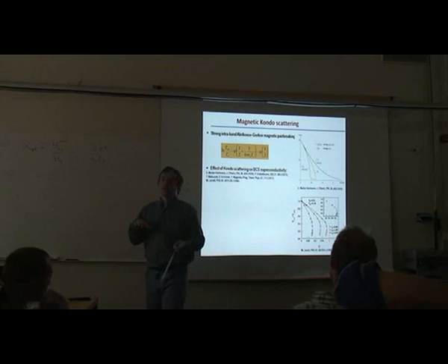And that is based on old theory of Kondo effects in a single band superconductor. In a single band superconductor, the theory of the Kondo effect has been developed in the 70s. And the answer depends on the ratio, basically, the Kondo temperature divided by Tc. If the Kondo temperature is much larger than Tc, then the Kondo interaction screens this scattering, reducing the pair breaking effect. So then, if the Born approximation shown here is like this, then if the Kondo temperature is high, actually Tc is less suppressed.